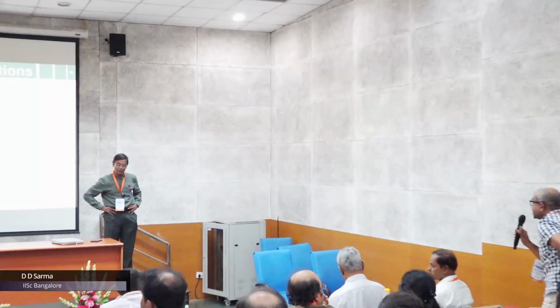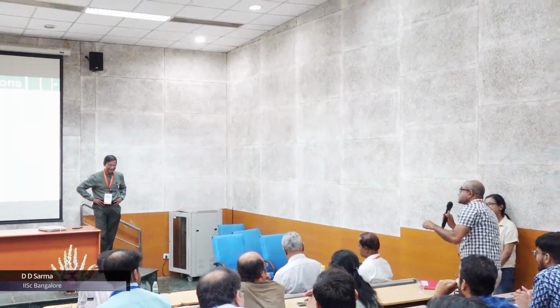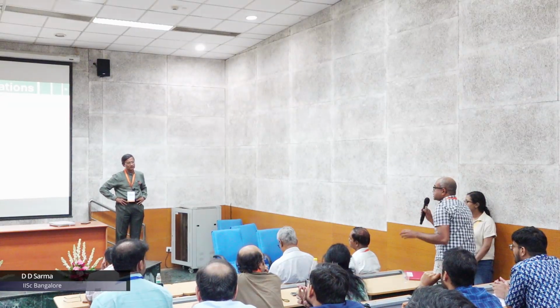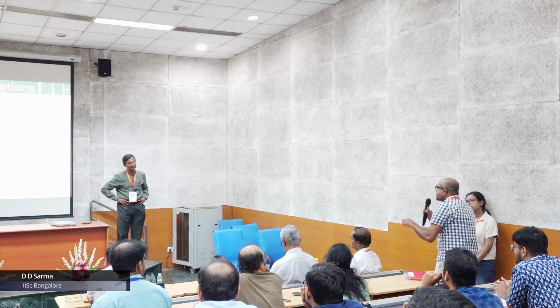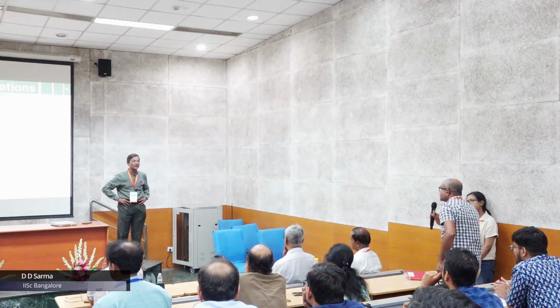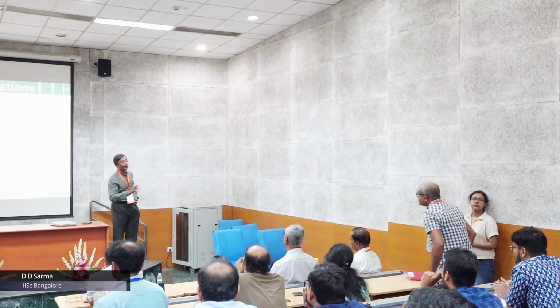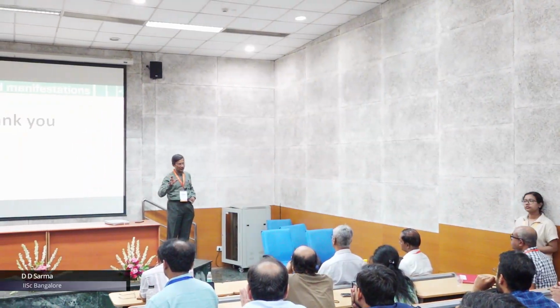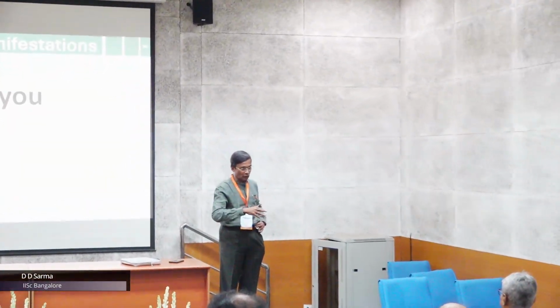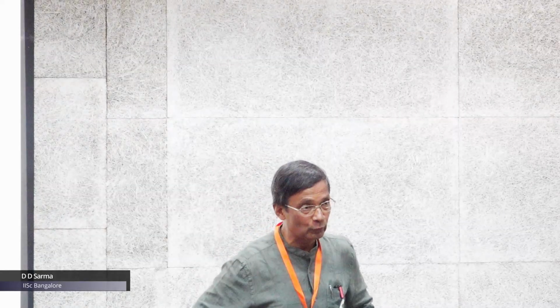Rajiv, one question. It may sound like a very naive question. Correlation physics is very important, but I'm not following this field: is there any magnetism present in this system? Absolutely. Magnetism is used as a standard probe. In the M1 phase, because all the vanadiums dimerize, the susceptibility just drops off. You get a Pauli susceptibility in the high temperature rutile phase where there are some moments, and the dimer is a singlet. So you get a first order transition into a totally different magnetic state, and we are using magnetic probes to understand that. It's done quite extensively.